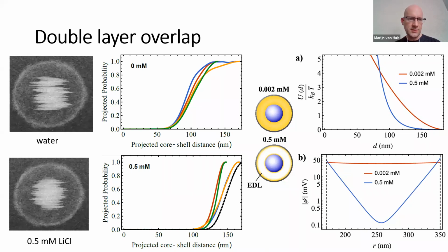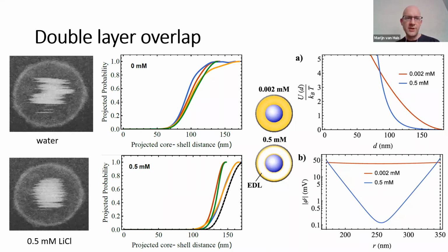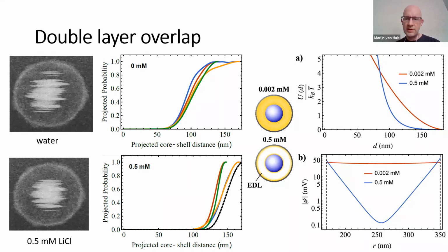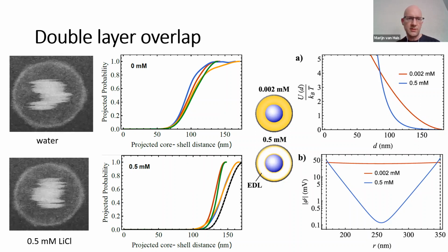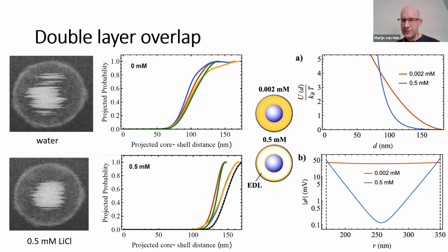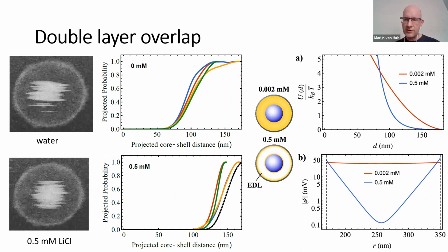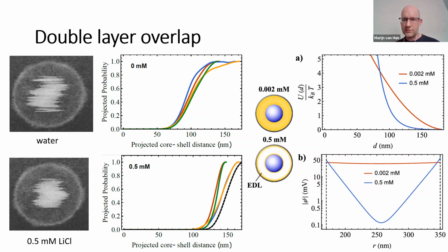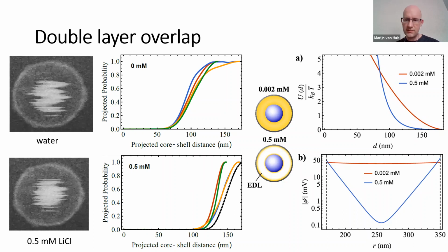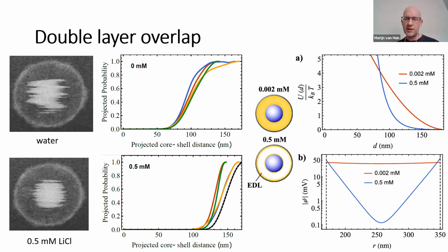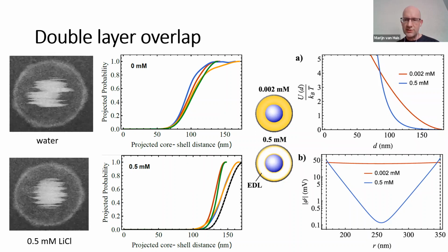And that is the reason that in pure water it actually has more freedom to move around, because the potential is being lifted over the entire volume of the cell. While in the case of added salt, we are limiting the range of the electrostatic fields by increasing the ionic strength. We reduce the Debye screening length.